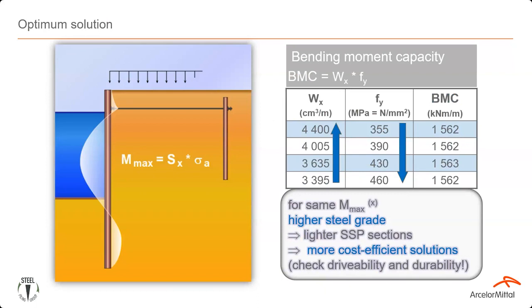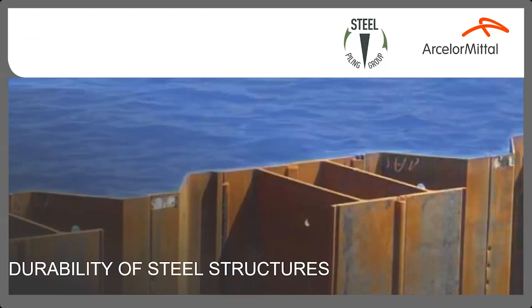Now, of course, there is an optimum solution. If you're designing with sheet piles, say you need a bending moment capacity of around 1500, and you've got 4 different pile sections using 4 different steel grades. Now, as a rule of thumb, always go for the highest steel grade. It's always more efficient, but maybe 2 things that you need to check is that you're not installing something that's too thin, as when you're using a higher steel grade, you're also using a thinner sheet pile section, and maybe also check your durability, because you need to check that you're not installing something that's too thin over the lifetime of your sheet pile.